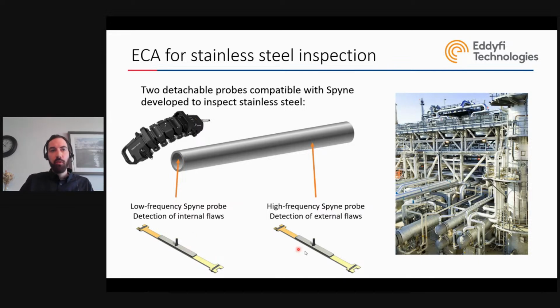We developed two of those probes. The first one is a low frequency probe. If you're familiar with eddy currents, you know that at low frequency you allow penetration into the wall. So with this probe you are able to inspect the ID, basically internal flaws. You inspect from the outside always, but you penetrate the wall and detect cracks on the inside. And with this second probe, it's the opposite. You also inspect from the external side, but you bring your eddy currents to the very top surface to inspect for SCC on the external side.